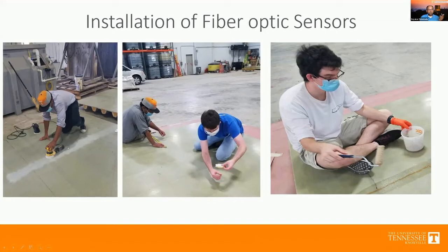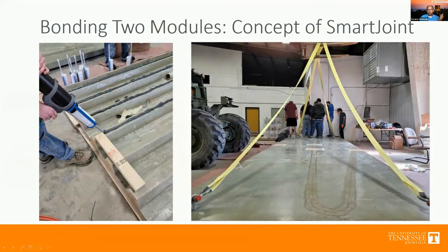So essentially, we use some kind of sanding to remove the surface oil and contaminants, then lay down the fiber and use a high temperature epoxy to bond them. You can see that wherever the fiber is, you measure the strain in that direction. And we have certain IP where we can measure the complete strain tensor with a certain configuration of putting these sensors in composite panels. Then these two decks are glued together with a structural adhesive.